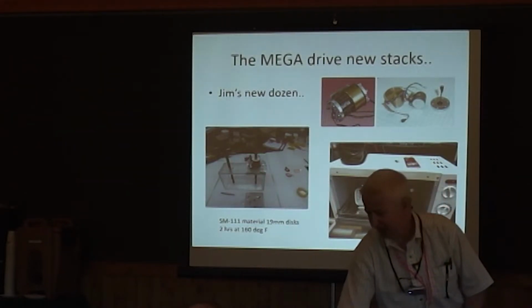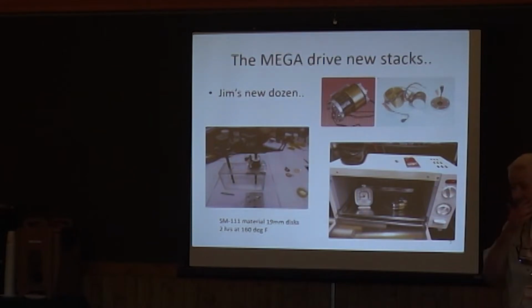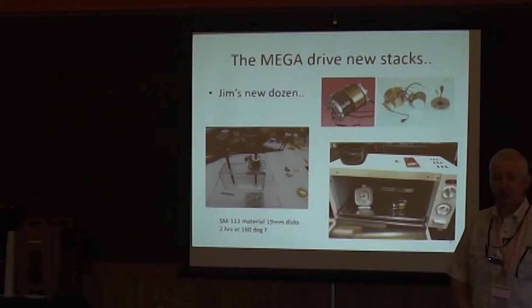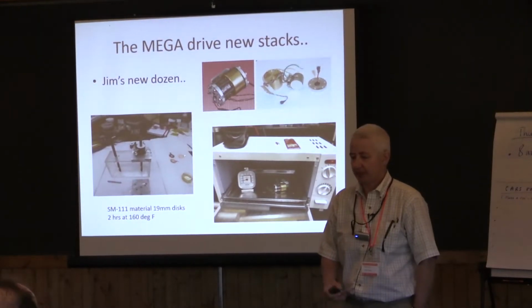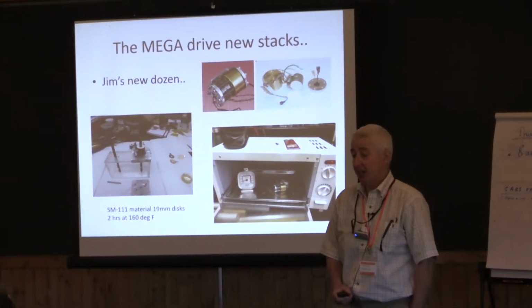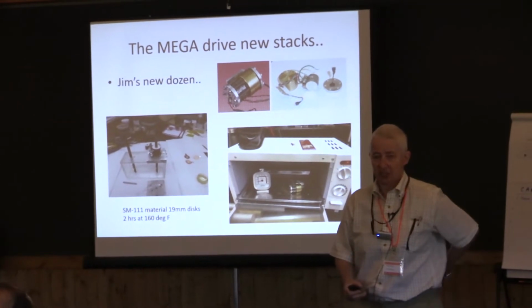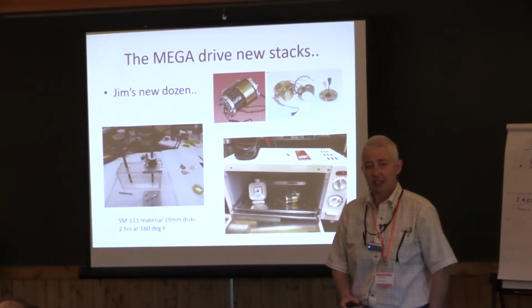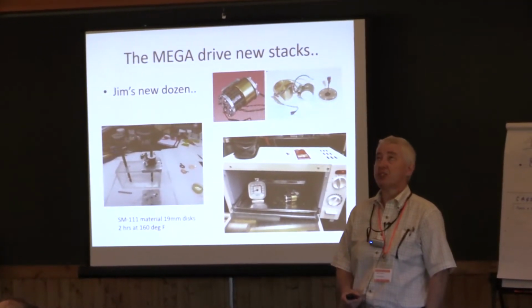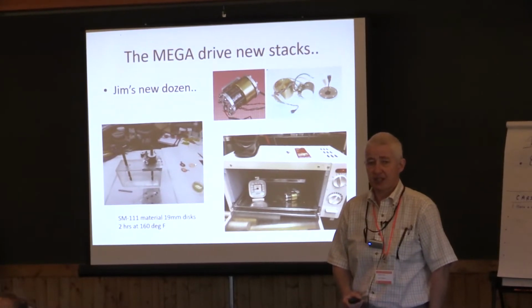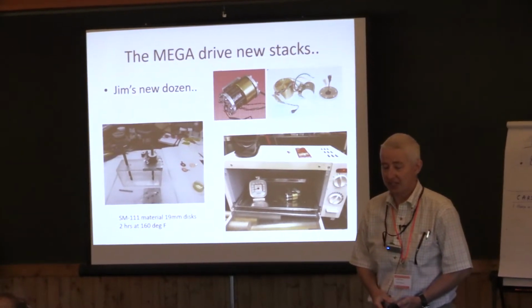Something about the epoxy, by the way. It turns out that Jim had been using an old method of curing the epoxy. He was told by an expert in the field that you're supposed to let it sit for a little while and then stick it in an oven and heat it at 160 Fahrenheit for 2 hours. Now that appears to have changed over the years.